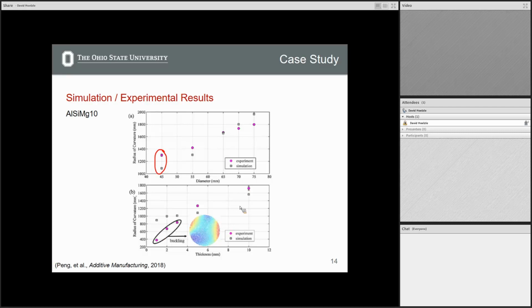And then as we go up in thickness, the radius of curvature goes up. And then out here, off the chart, we decided not to report these values at, I think it was 20 and 30 millimeters, because the deformation was so low that we couldn't actually fit a sphere to it. So it was essentially a flat structure. The radius of curvature measurement was really kind of fictitious in that extreme.